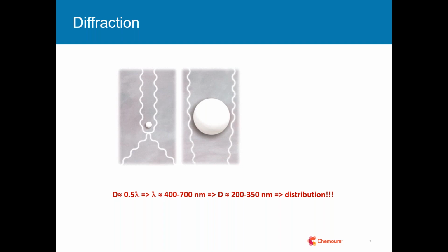If we blow up the particle, we make it much larger, the light essentially will just pass through, will only very slightly change in direction, and it will not be efficient in scattering. As there is a distribution of wavelengths, we also need a distribution of particle sizes. Otherwise, we would, strictly speaking, scatter only a limited number of wavelengths, and we will not come to a white coating. So, three mechanisms, very important.